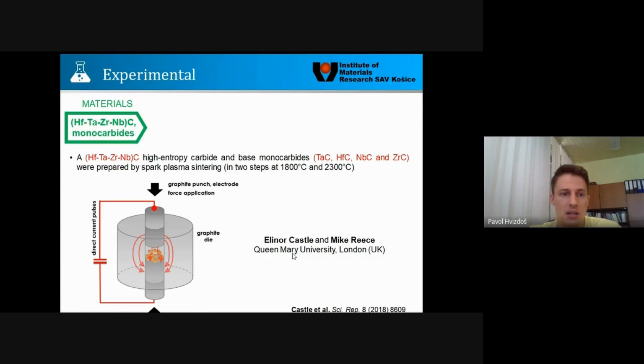The experimental techniques, what we used first was the synthesis of this kind of material. As I mentioned in the beginning, that high entropy carbide material was synthesized by our English partner in London, using a two-step spark plasma sintering technique. And at the same time, there were also base monocarbides synthesized. So hafnium carbide, tantalum carbide, niobium, and zirconium carbide, just as a comparison of the mechanical properties, what we investigated later on.